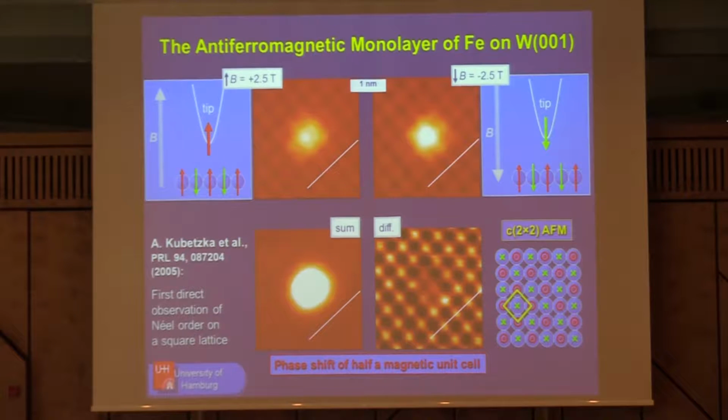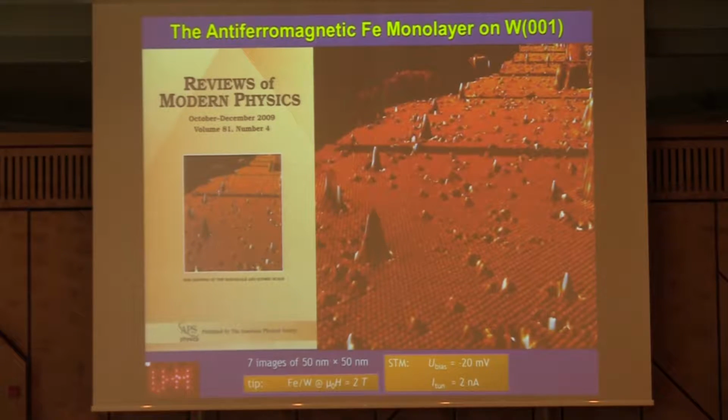To my knowledge, it was the first real space observation of this kind, and we could do so not only locally, but because of a significant improvement in the signal to noise, we were able to observe large-scale images with atomic resolution spin contrast, which you see here. But you see that on larger scales, of course, you have atomic defects, vacancies, impurities, adsorbates, single iron atoms on top and clusters, as well as these second layer islands.